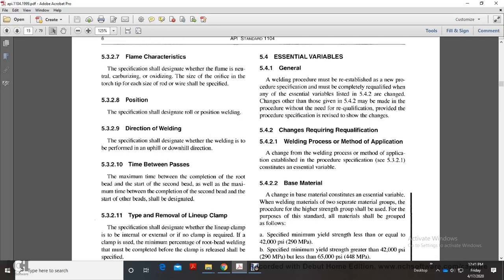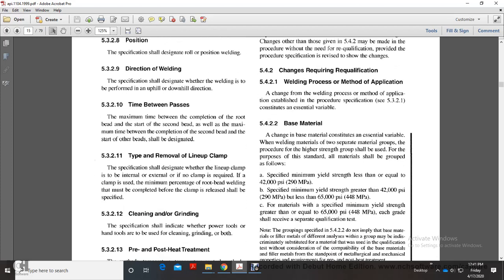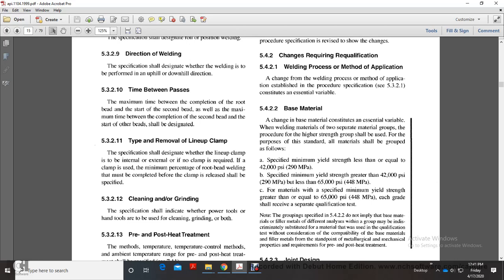5.4.2 Changes requiring requalification. 5.4.2.1 Welding process. A change of the welding process or method of application established in the procedure specification, 5.3.2.1, constitutes an essential variable. 5.4.2.2 Base material. A change in base material constitutes an essential variable. When welding materials of two separate material groups, the procedure for the highest strength group shall be used for the purpose of this standard.